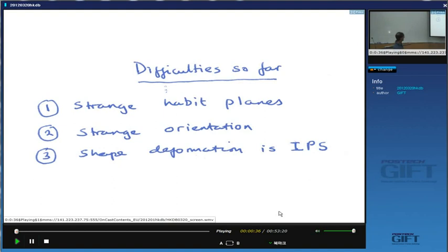We also noticed that the orientation relationship is irrational. In other words, the closest packed planes from the two lattices are not exactly parallel. They're approximately parallel. Why is that? And I showed you some images of the shape deformation which happens when austenite transforms to martensite. And when we measure that accurately, that's an invariant plane strain. That means it appears to leave a plane undistorted and unrotated.